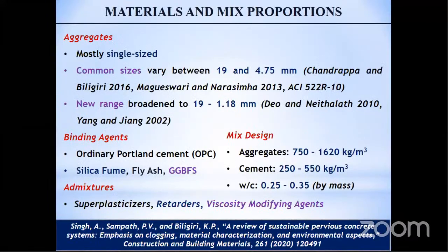Moving on to the materials and mix proportions. Pervious concrete is mostly designed with the use of single-sized aggregates. The most common size ranges for pervious concrete vary between 19 and 4.75 mm. However, recently some researchers are trying to incorporate sand into the mixture, and the range has been broadened to close to 1.18 mm as well. Some other studies have further utilized fine sand of true gradation, but the dosages at which it has been added are relatively small, most of them restricted to up to 10% by weight of coarse aggregates.